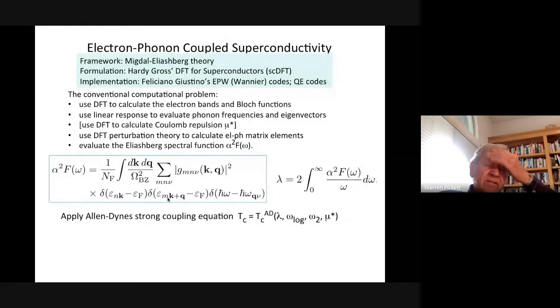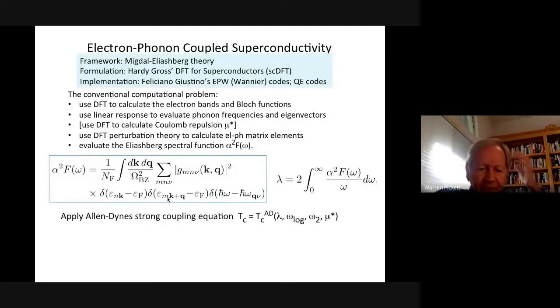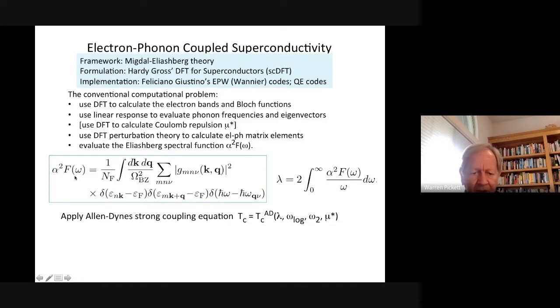So let me just give you an idea of what is involved in the calculations. I won't go through these things here, but the key quantity function that needs to be calculated is called alpha squared F, and it's a function of frequency. This is phonon frequencies, so there's an upper limit of whatever it is, 100 meV, milli electron volts, give or take a factor of 5, depending on your material. But what you need to do to calculate this is the electron phonon matrix element. So this has both electronic properties and phonon properties in it.